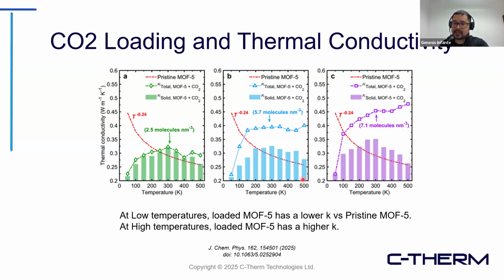So, as you go through this chart right here, the difference between the green, blue, and the purple is effectively the rate of gas diffusion within the system itself. So you're increasing the gas diffusion. You can see that all of a sudden, as you're increasing that with higher temperature, the conductivity is now trending in a more increasing path, right? So there is that correlation on not just the MOF structure itself, but the gases being involved, in this case CO2, and the rate and amount of gases involved at the temperature that you're measuring.